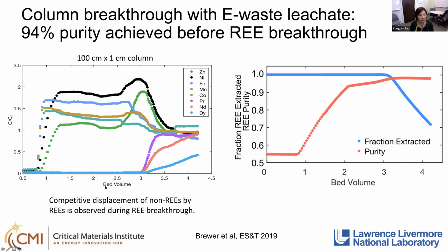A couple of observations from this breakthrough curve that I'd like to note. One is that the breakthrough time of the rare earth is very different, is much later than that of the non-rare earth metals, indicating selective recovery.